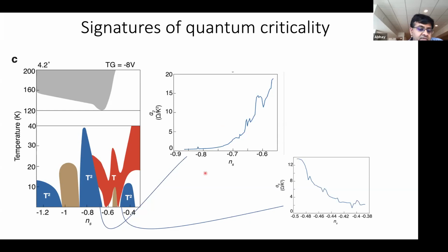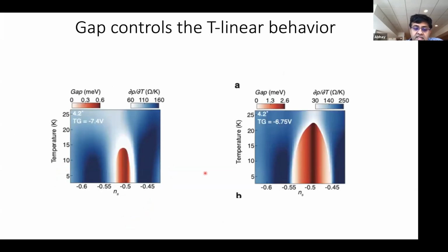So really, it looks like many of the beautiful experiments that were done in heavy fermions have a very nice parallel to the transport data here. One or two final last things. We can change the size of the gap by applying this electric field, as I said. And if we do that, we find that the slope of the T-linear behavior is controlled by the size of the insulating gap. Again, telling you that this correlated behavior that gives rise to the gap at half filling is really the thing that's responsible also for the T-linear behavior.